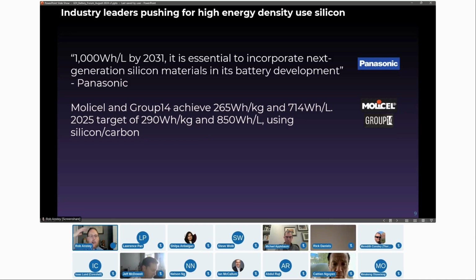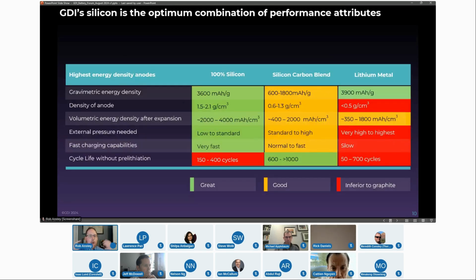Then, at the conference, the crowd asked, well, what's the limit, Molicel? How much silicon do you think you can actually get in a cell? And Moly said 20 to 30%. At that point, it's really going to cause issues with expansion, contraction, the foil, and other things. So therefore, their target is 290 and 850 watt hours per liter using Group 14 material. Well, that by definition isn't going to get you to 1,000. And why is that? It's all math.